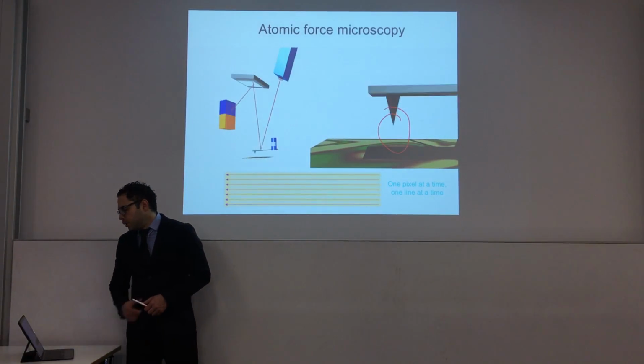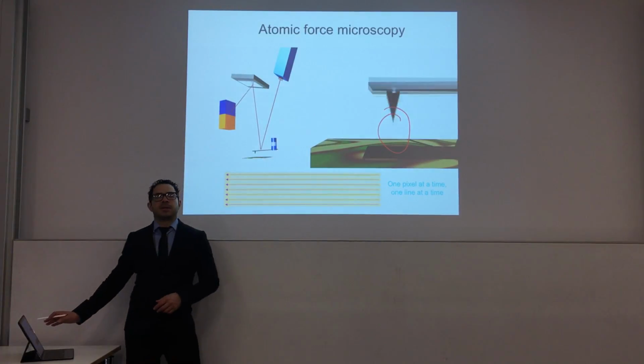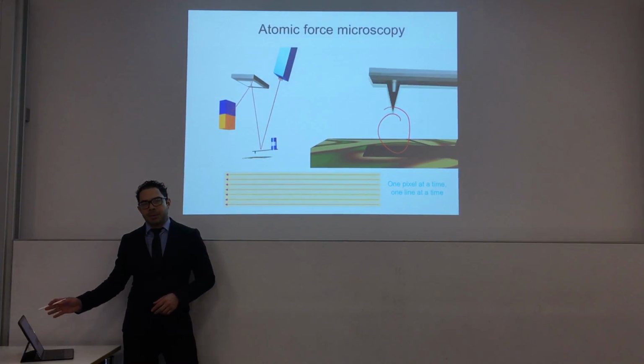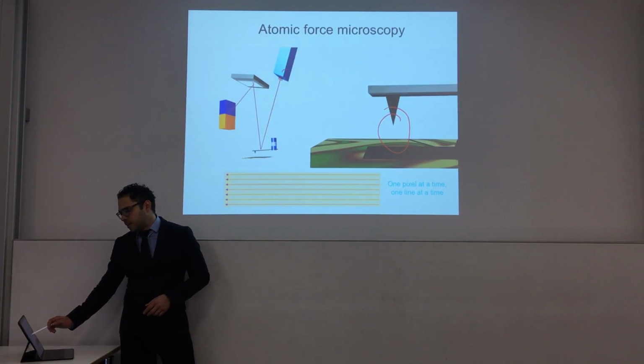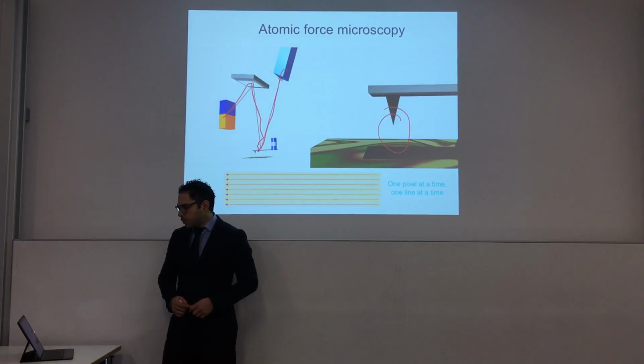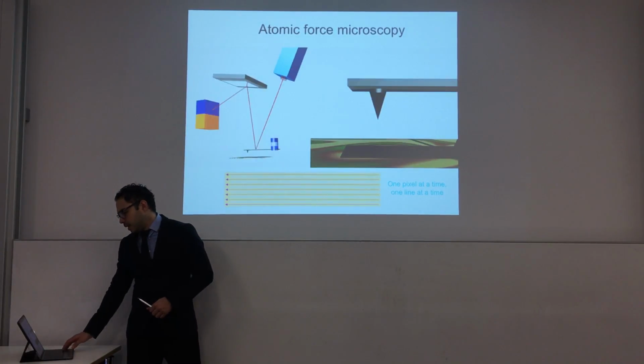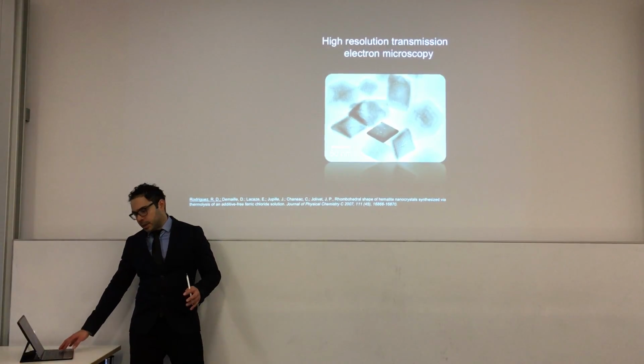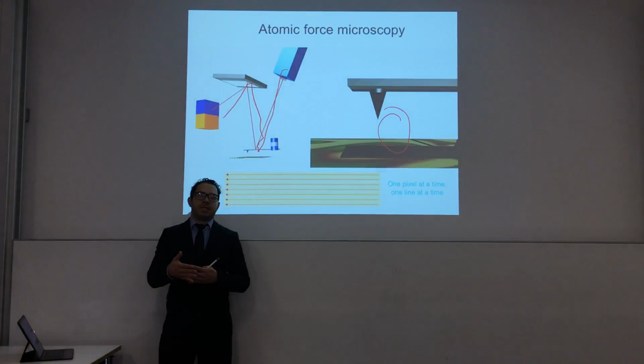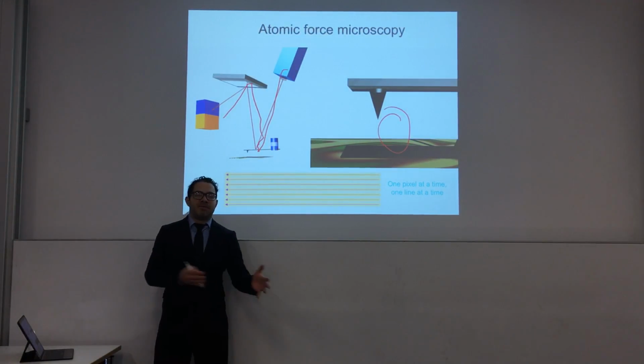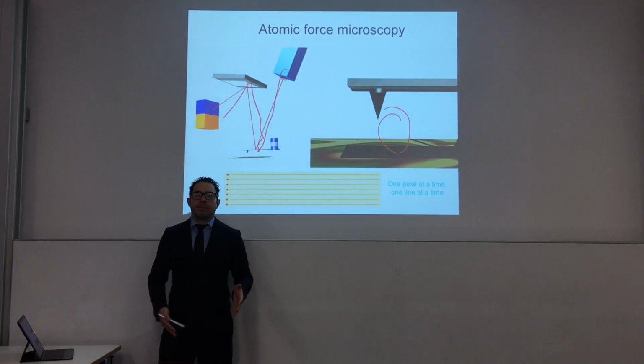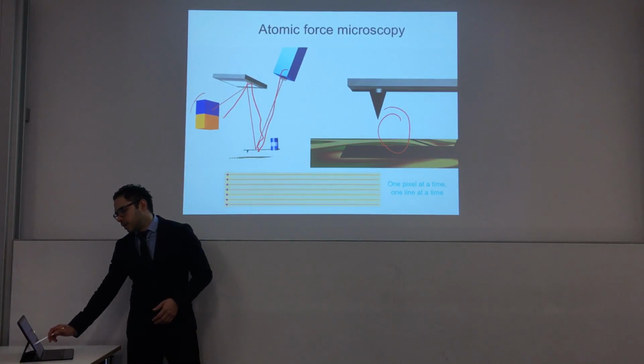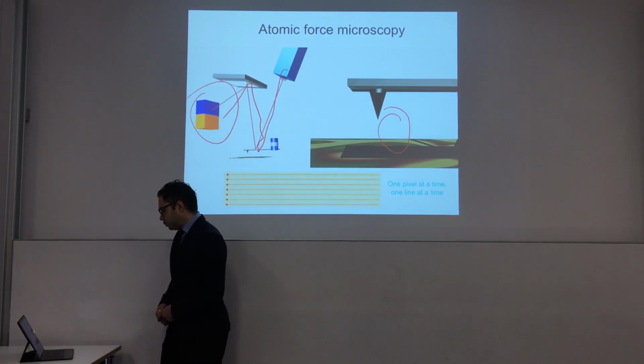The way we follow the deflection of the cantilever is using what is called the optical lever system. You have a laser that reflects on the back of the cantilever, then a mirror, and then goes to a photodetector. So very small changes in the cantilever, up to 0.5 nanometers, for example, you can amplify using the optical lever system up to millimeters that you can easily detect in a photodetector.